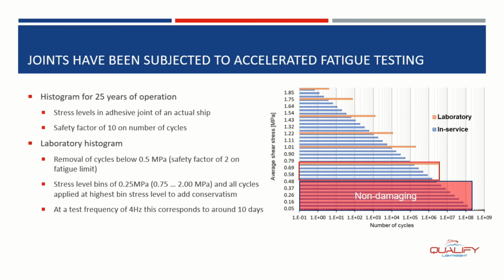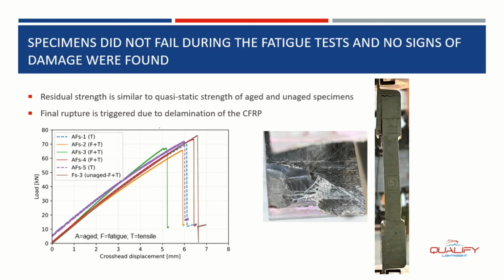In that way, we binned the load schemes and tested the joint at 4 Hertz. That means that 25 years of operation with a safety factor of 10 could be reduced to a testing time of 10 to 11 days, if we test 24 hours a day. All the joints that have been fatigue tested, I show you here the tensile tests, survived the fatigue loading completely.